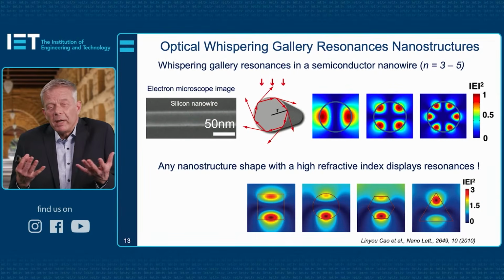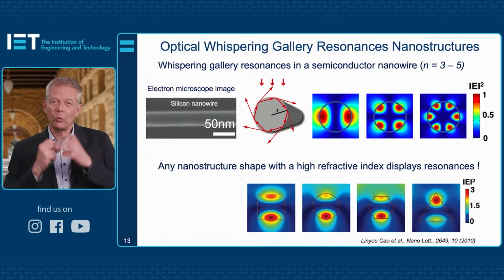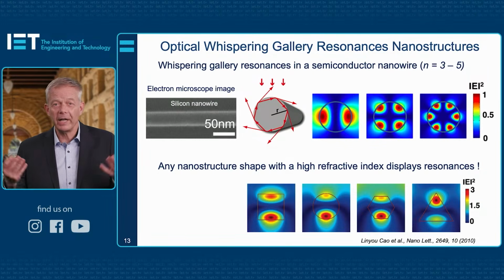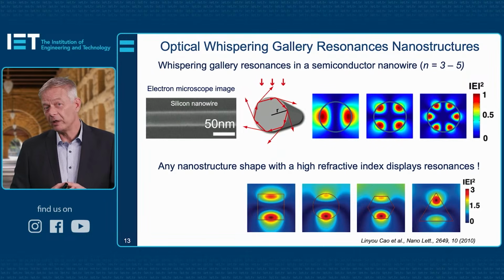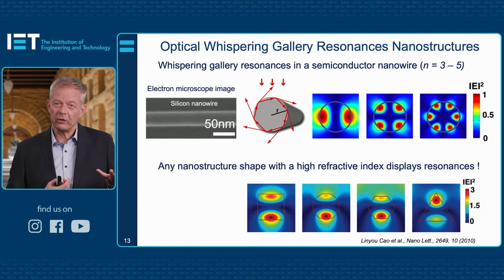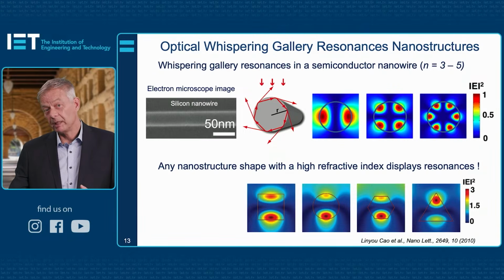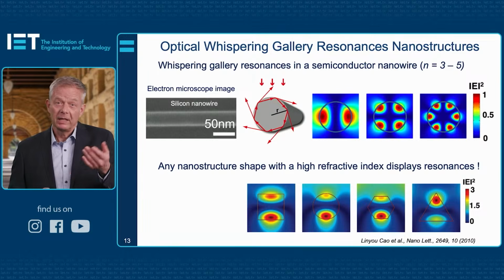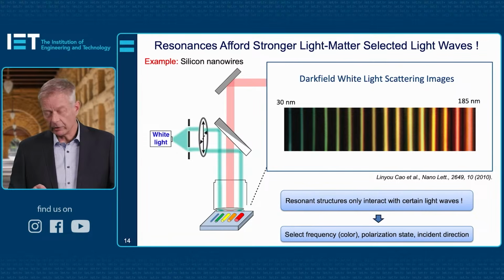And we can use the circulation of light in the semiconductor to enhance absorption or to enhance scattering, depending on the wavelength of light. One very nice thing is that no matter what nanostructure shape, whether you take something with a square cross-section, hexagonal, circular, triangular, all of these nanostructures display these resonances and allow light to bounce around a little bit inside the nanostructures to boost light-matter interaction, to get enhanced absorption, scattering, or possibly even emission if it's a light-emitting nanowire.